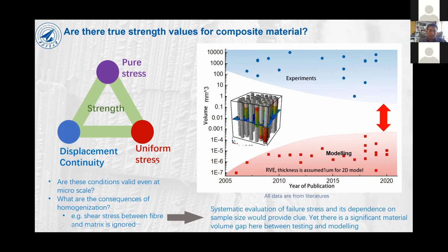And again, do we have a uniform stress? Not so either, because of many challenges associated with current experimental capability. And again, of course, before any fracture happens, there is this displacement continuity. So the question is, do we have all these three valid at the same time at a unidirectional lamina scale, or if you look further, zoom in at a single fiber and matrix scale? And the thing is, when we talk about strength of a laminate, we have involved this homogenization process.